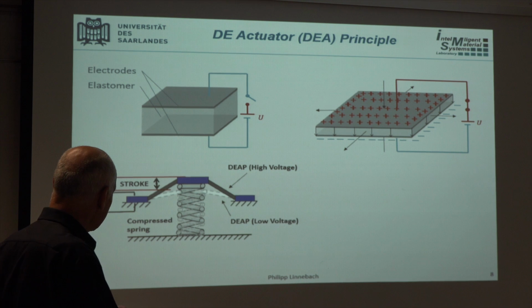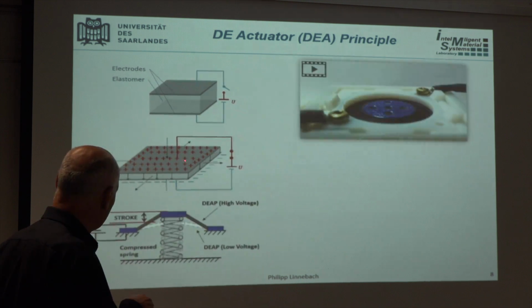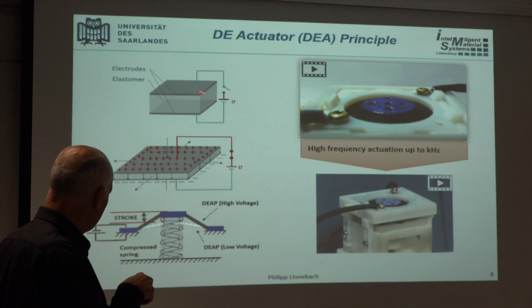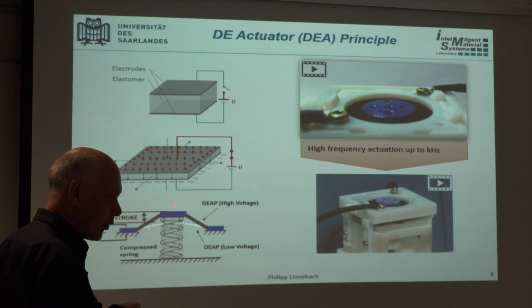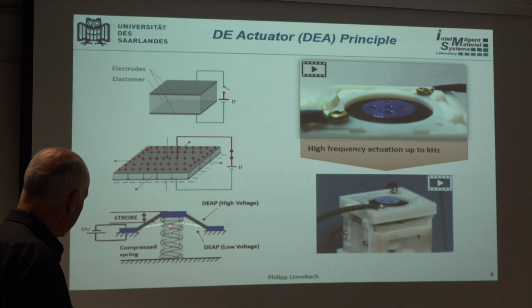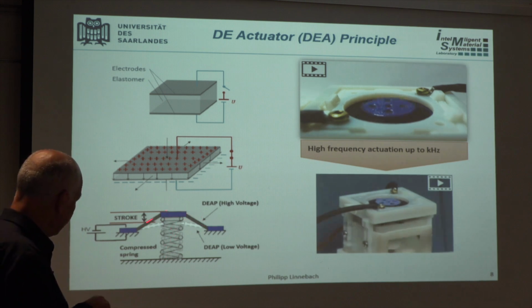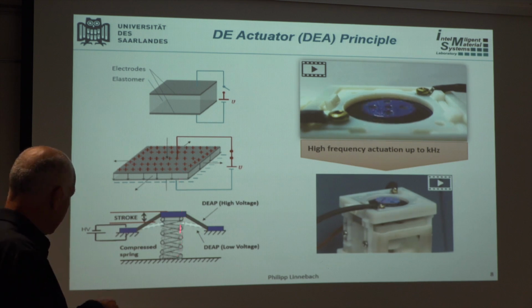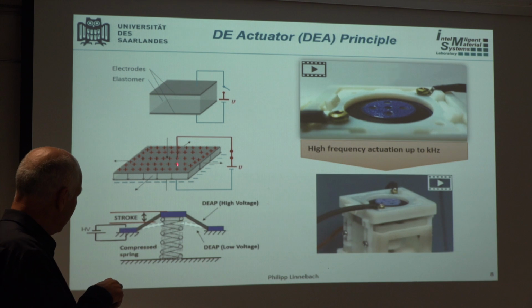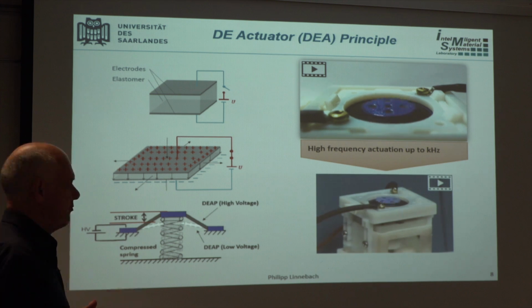If I show this again, in order to make it work in terms of actuation, we have the sandwich that I mentioned before, and you see that even though it's a membrane, you can get out of plane actuation from it if you place some kind of a bias mechanism underneath. In this case, that's a little spring. The spring deflects it out from the plane, and then when you apply a voltage, the material gets compressed and the spring can actually push it up a little, and when you remove the voltage, the elastomer compresses the spring back to its original state, and you see you get some kind of pumping motion, valve operation, something like that comes to mind immediately.